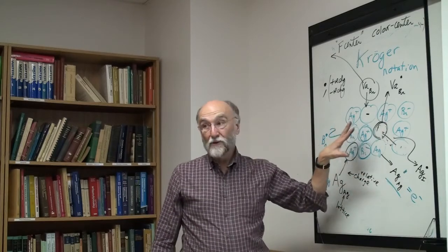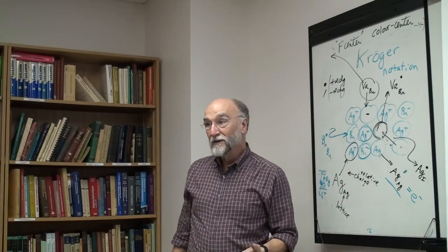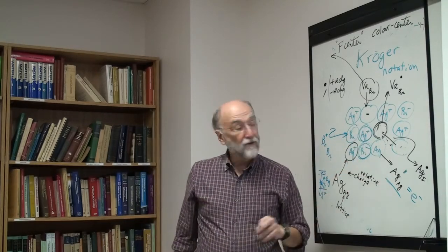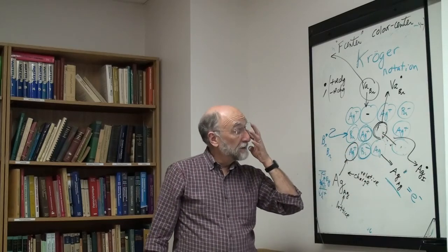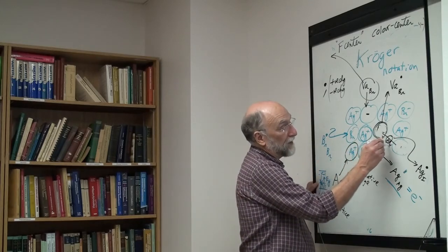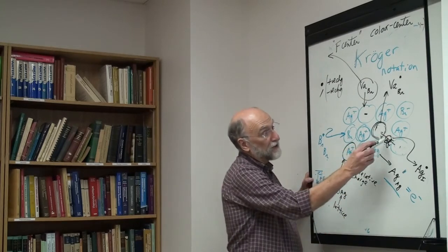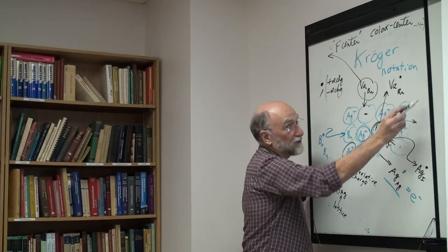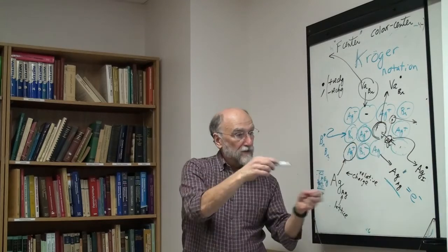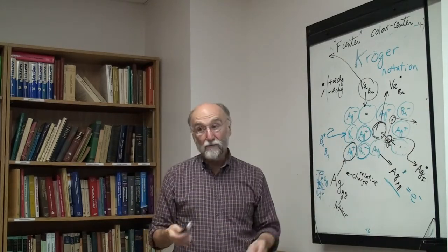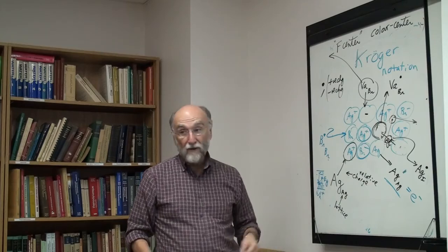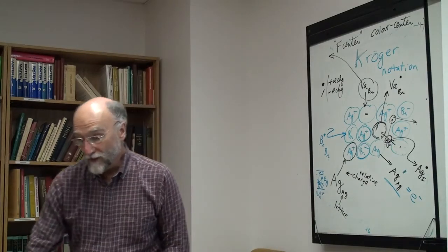If you have a perfect crystal with no defects, your diffusion coefficient is basically zero. The things can't move. The only way things move in an ionic crystal is by hopping. Either ions can hop, or electrons can hop with electronic conduction. Similarly, if you have a silver, say, in an interstitial site, then it can easily hop to a neighboring interstitial site, then move to the next interstitial site because there's nothing there. So interstitial defects can hop, and vacancies can hop by simply the next atom moving, and that gets you both diffusion and ionic conduction. If you have these neutral silvers and bromines, that gives you your electronic and hole conduction. And that's the notation it gives.